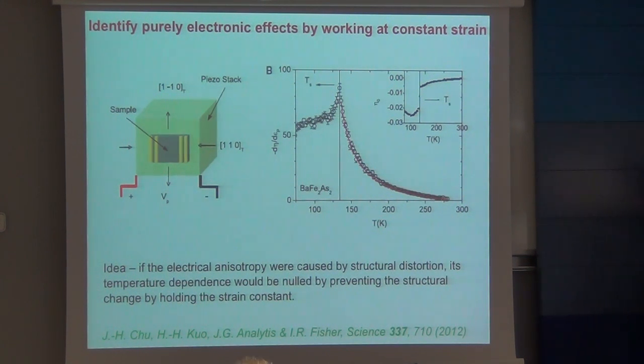Sorry, Anne. Yes? This also means that the crystals are very sensitive to strain. So there's pressure or whatever it will. Yeah, indeed. The pnictides are extremely sensitive to strain. All of these arguments are based on symmetry, and symmetry doesn't tell you the coefficients. So there's some unknown parameter that tells you the strain sensitivity. Some of them are strongly sensitive, some of them aren't. And so obviously if they're strongly sensitive to strain, then there must be something pseudo-structural going on here, even though it's not driven by the positions of the nuclei.